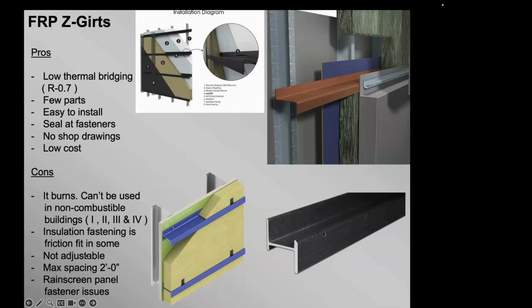There's no adjustability in these. You're going to have to shim every panel. The maximum spacing is 2 foot. And one manufacturer has an FRP one, I'll show you that a little bit later. They cite a paper by the American Society of Civil Engineers that says if you put a screw through an FRP product, the FRP product will fail because you're breaking up the resins in there. I don't know why they did this, because theirs has FRP too, and they put a screw through it.